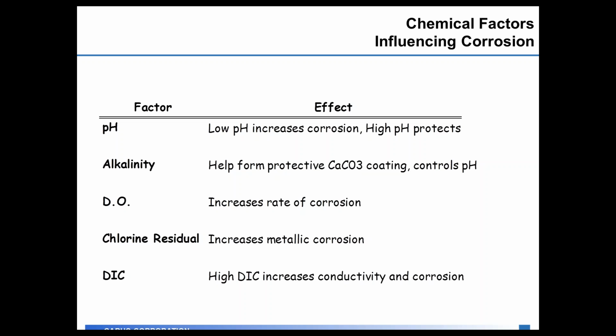Finally, DIC, or dissolved inorganic carbonate, is a measure of the conductivity of your water. What it's looking at is the higher your DIC, it actually interferes on the types of things you're doing for corrosion control. One of the new things in the US EPA document for optimal corrosion control is the DIC of your specific water, knowing that if the DIC is higher in one water over another, you might have to do multiple things to make the water less corrosive. So you may look at pH adjustment, alkalinity adjustment, and adding a corrosion inhibitor in those waters with higher DIC in order to get corrosion protection for lead and copper in the distribution system.